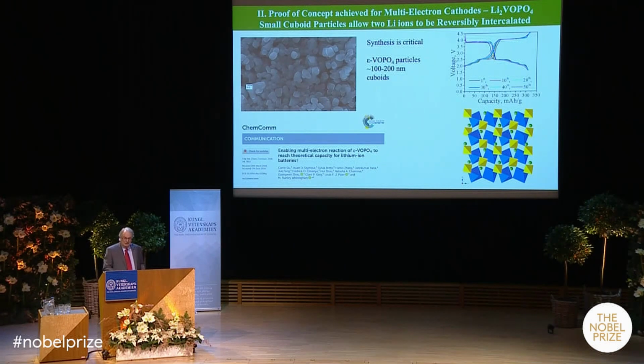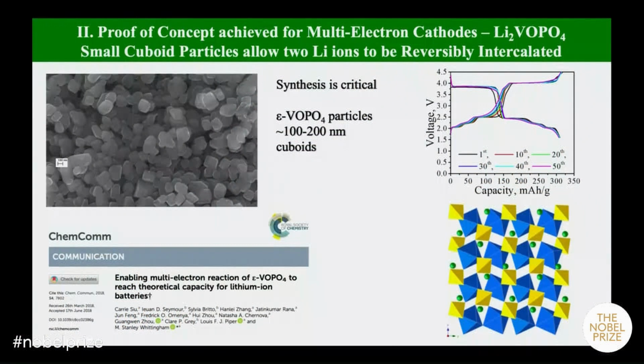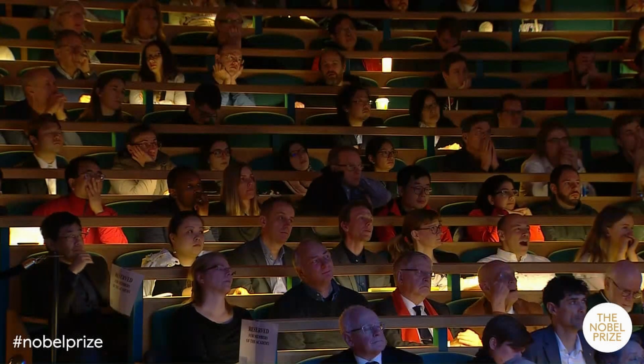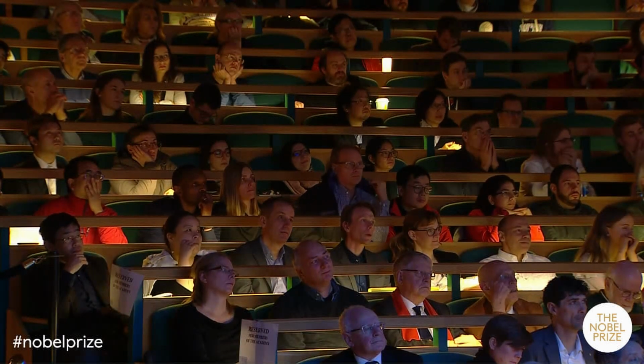Similarly, we started looking at can we stuff 2 lithium ions or 2 sodium ions into many of these structures. And we looked at vanadium compounds, because vanadium can go from 5+ to 4+. And we had students working on this for many years, and they found out we made these little cuboids. These are about 100 to 200 nanometers in size, and you do it the right way, so the synthesis is critical.